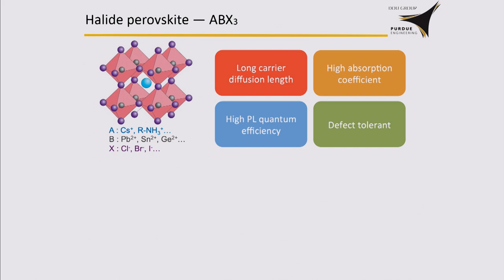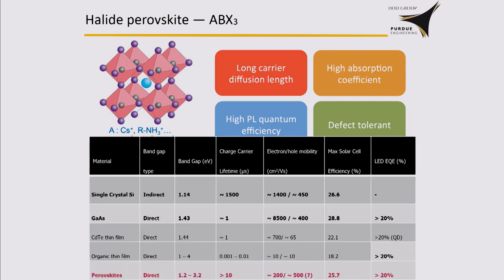But interestingly, if you use the combination of lead and the halide, it shows wonderful optical and electronic properties and is almost ideal for solar cells, LEDs, and many optoelectronic device applications. At least some of the semiconductor parameters here, I won't go through the detail, but basically I want to show that these materials are obviously much better than other conventional thin-film semiconductors, and some of the properties are approaching single crystalline silicon. For example, for solar cells, people are very excited about this.